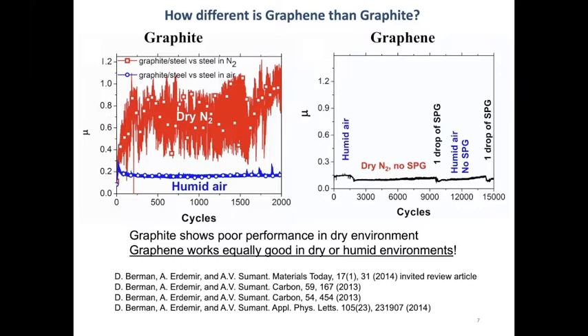The major reason for this is that for graphite, in order to get this good lubrication, you need to have enough intercalation of water layers to smoothen the surfaces and allow easier sliding of the graphite flakes. In the case of graphene, what we observe is that whenever we're transitioning between humid and dry environments, we get very nice sliding at pretty much the same level, with low friction, low wear behavior. And one interesting thing is that whenever we start to observe some wearing of our material, we can easily replenish it by putting additional solution-processed graphene on the surfaces, by drop casting or spraying these materials or injecting them into the system. It allows us to get this low friction sliding for as long as needed.